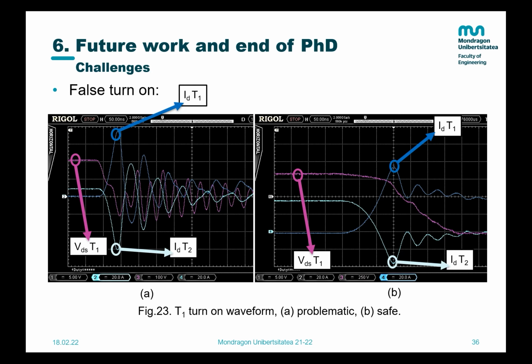The first challenge that we faced was the false turn on that I show in the left-hand side here. This is the very first switching that we did with silicon carbide. It's a very low current switching, but as you see, there is a short circuit here with a huge current spike. This is because the switching of the lower switch turns on the upper switch. This phenomena will hardly ever happen with silicon IGBTs because the switching is so slow that the switching of one device is not affecting the switching of the other device.